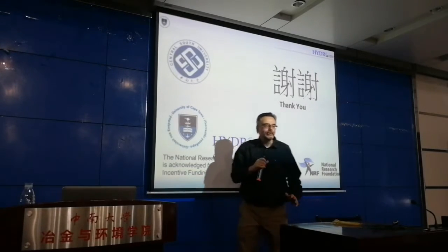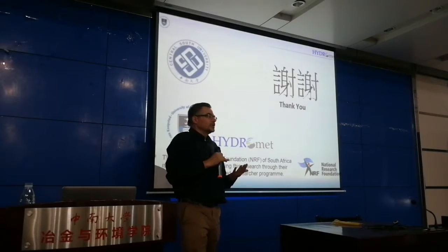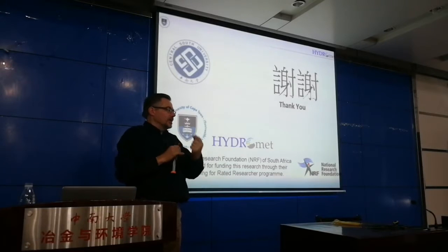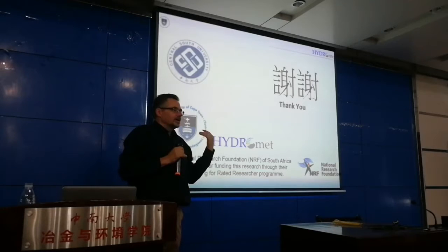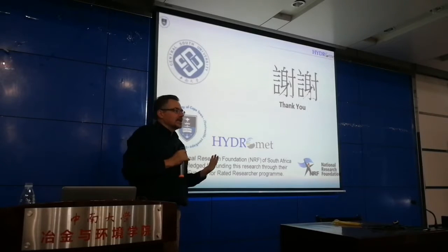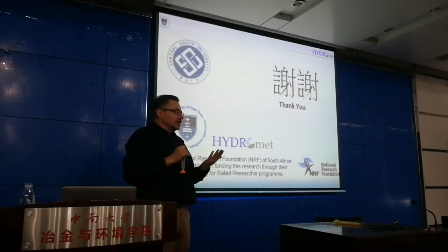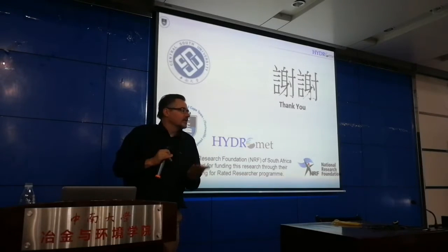How efficient you have to operate a heap in a given context depends very much. It's different from case to case. So you need to understand always what are you comparing it against. So in the example that I gave, we looked at a medium grade zinc sulfide ore. It had an average zinc grade of about 9%, which is quite high. And so for zinc grade like that, conventional flotation and preparing of a concentrate is still a viable process.